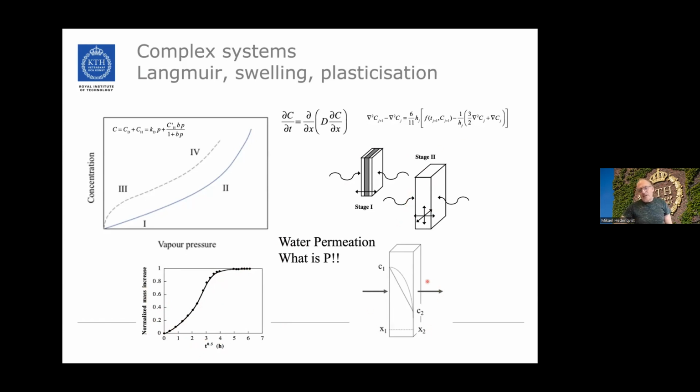And another thing that I have to point out here, because it's used a lot in actually not a correct way. When you calculate the permeability of water in polyvinyl alcohol, for example, you are calculating it based on that there is a linear concentration gradient between the high concentration side and the low concentration side. That allows you to relatively easily calculate the permeability.